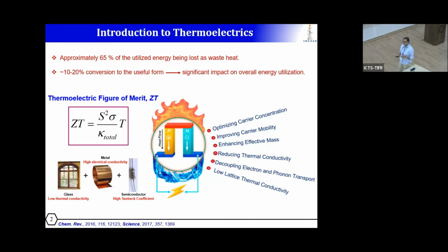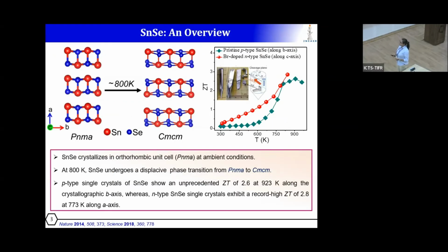Till now, several strategies have been adopted to enhance the power factor of a thermoelectric material by optimizing the carrier concentration, improving the carrier mobility, or modulating the band structure. Simultaneously, the thermal conductivity can also be decreased by nanostructuring, or by introducing point defects, grain boundaries, etc. But the problem with the marketed thermoelectric materials is that most of them are based on tellurium. Tellurium is highly toxic, costly, and less abundant in the earth's crust. So I have started to work on SnSe, which is a cost-effective and eco-friendly material.